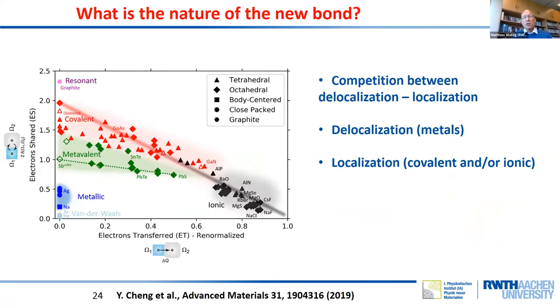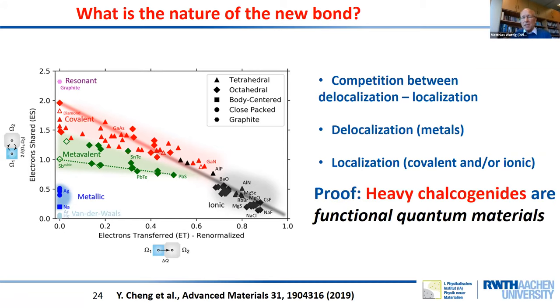So what's the nature of the new bond? We all know that in covalent and ionic compounds, there is localization of electrons either between the atoms, that's covalency, or at the ion cores, that's ionicity. Or there's delocalization as in metals. This green region is the competition zone. Yeah? We have a competition between delocalization and localization. And this proves that we have functional quantum materials, defined by this competition between delocalization and localization.